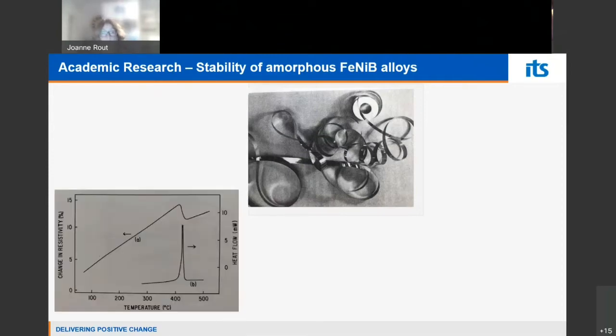The studies I did were kinetic studies, looking to see how stable these materials are and what happens when you crystallize them. It was quite academic. I'd be looking to model the crystallization, the nucleation and the growth, using experimental techniques to look at how the crystallization progressed, such as resistivity changes. Differential scanning calorimetry was a really good technique to observe the crystallization.